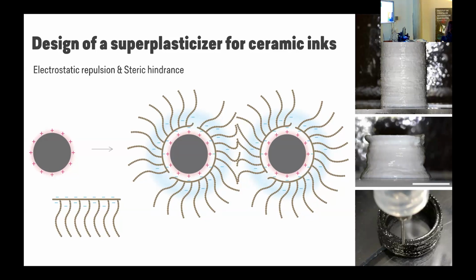They are using stuff like polyacrylic acid as the homopolymer form. They basically introduce the binders and such, and then they have good fibers, but they are really ignoring the effect of steric hindrance. It is a power that we have in material science, but we don't use it. It is just interesting to me. So in our previous work, we worked on these colloidal systems to maximize the amount of particles that you can introduce into the system. And there are calculations that tell you this is the theoretical limit that you could have in a suspension. And here we are almost at the theoretical limit with alumina. This is, I think, 83 weight%. And look at this, this is just 1%, 1.5% less.